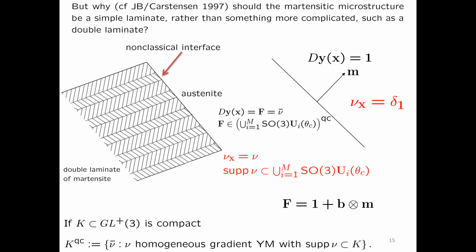So if you like, over here, everywhere you're using a martensitic gradient, which has zero energy. But you're allowed to have boundary layers between these things, which would vanish in the limit as j goes to infinity. Okay. Unfortunately, this quasi-convexification is unknown unless you have two variants, which is one of the problems about this theory,